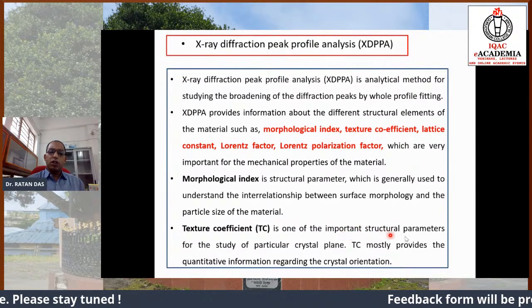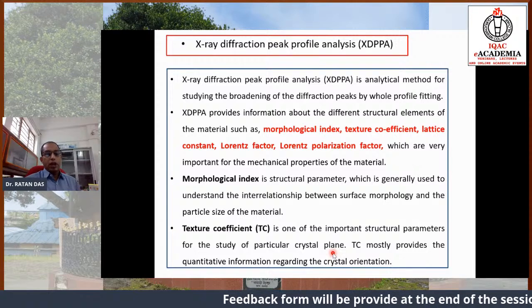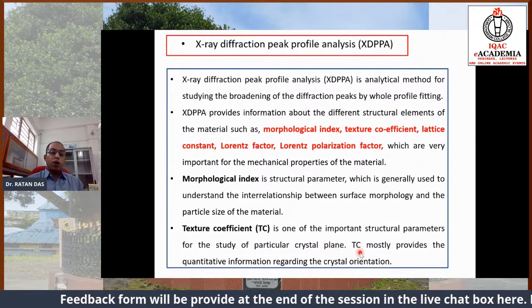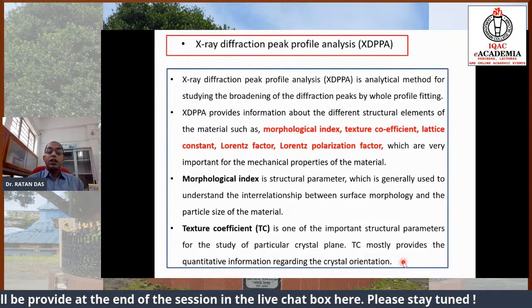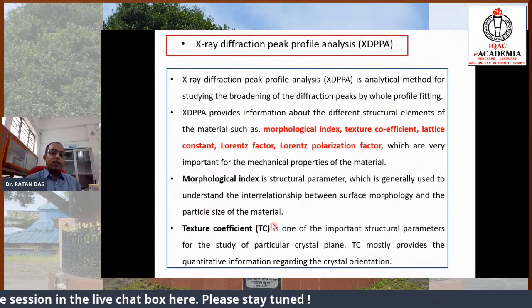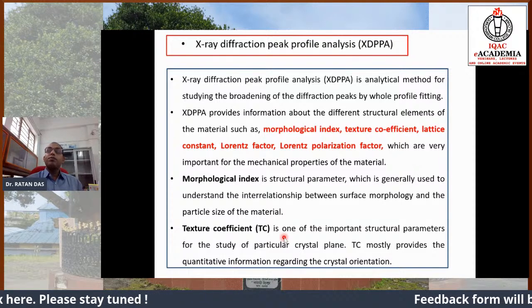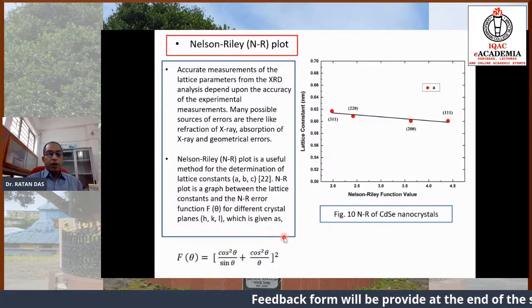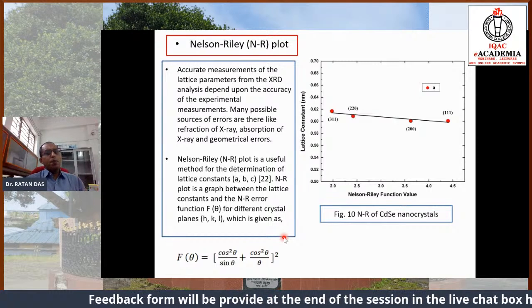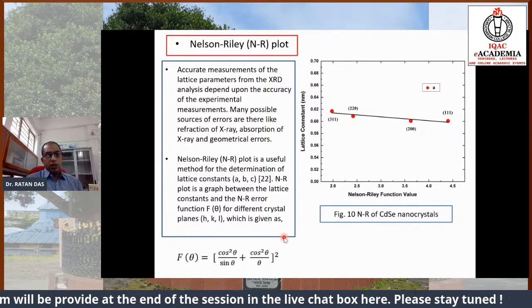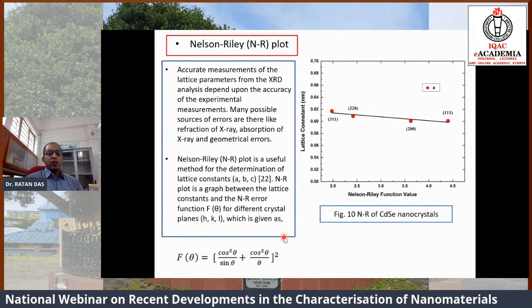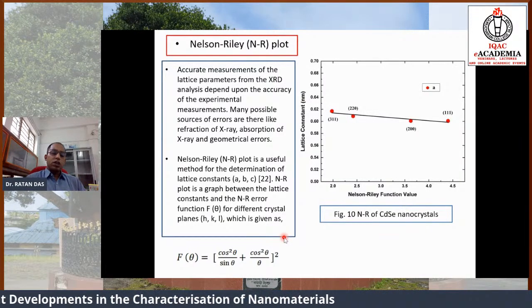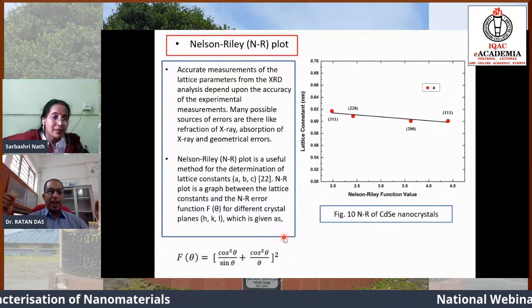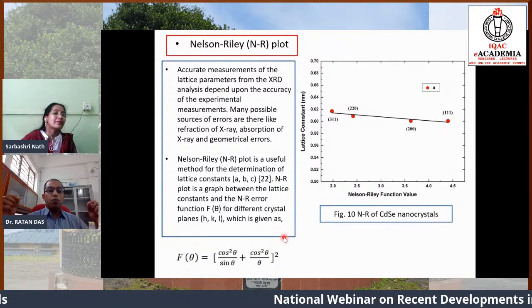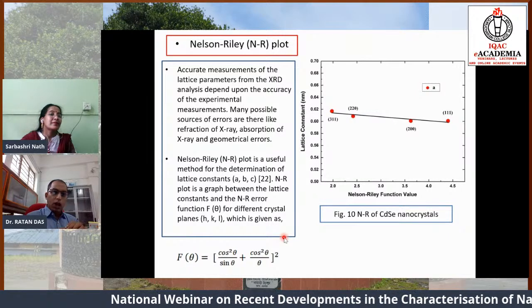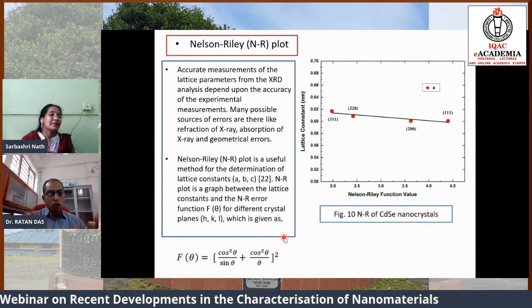The texture coefficient is one of the important structural parameters for the study of particular crystal planes. So the texture coefficient mostly provides quantitative information regarding the crystal orientation. That also can be obtained in the case of a powder diffraction pattern. Now, one of the important parameters is the lattice constant. Suppose we have a simple cubic, FCC or BCC crystal structure, then we have the lattice constant a. That value can be determined from Bragg's formula, or more errorlessly.